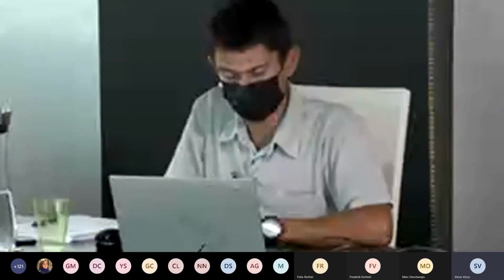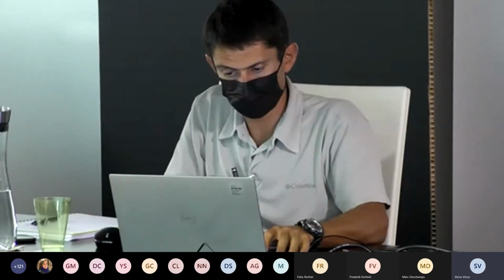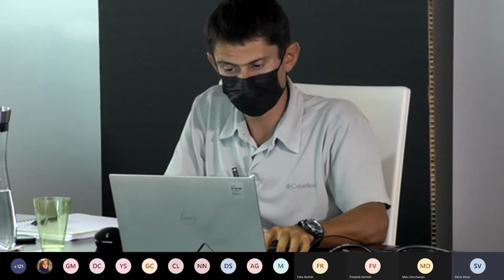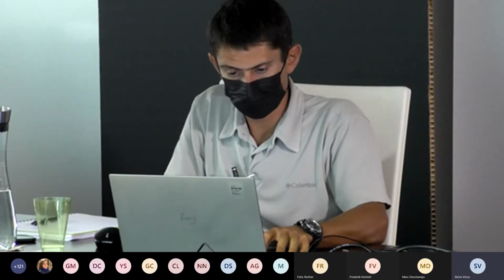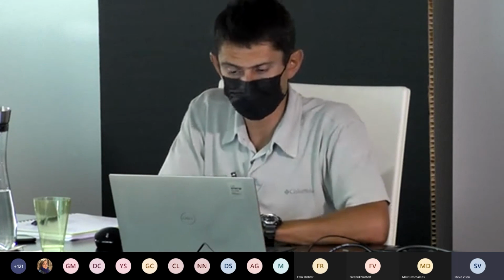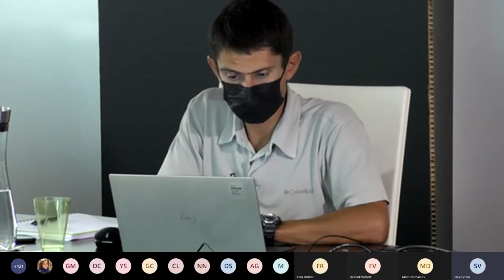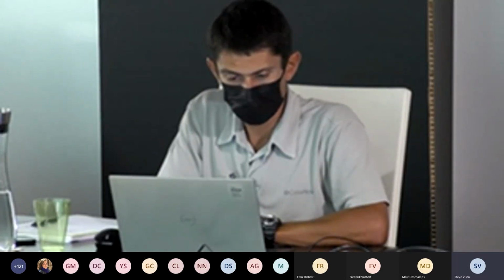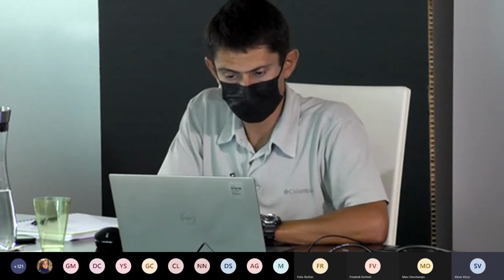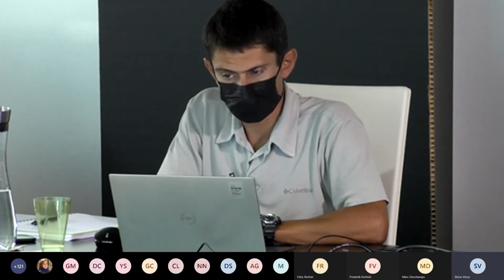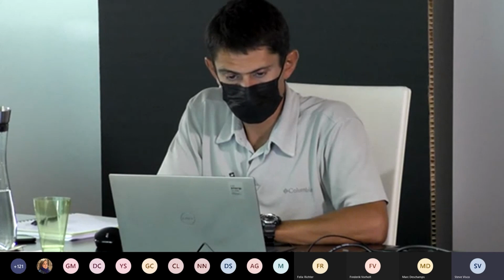Yeah. In fact, I put up one slide showing the measured modulus. We did some work with Eric Herbert at Michigan Tech, and we did nano indentation of the glass. And these glasses, in fact, are quite strong. So they're strong enough to block dendrites. And as I mentioned, when you get down to these dimensions, they're also quite flexible. So you can use roll-to-roll manufacturing.